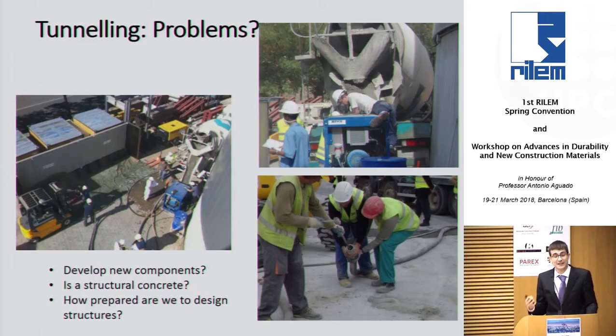Right? So we can spray at the lab here at the UPC. We sprayed many mixes here at the lab of the UPC. Some of those with more success, some with less success, as you see here, when we have this type of problem of blockage. This is me here, just to show that I'm working there, and here you have the pump. So we had a blockage in the pump, and I was with a vibrator needle trying to push it down. And the funny thing that happened here, I was pushing the vibration needle down, and when I pulled it up, the tip of it had been removed. So it was inside the pump, and it was pumped out from the system. Right? It was quite dangerous. But it's very nice, very interesting.